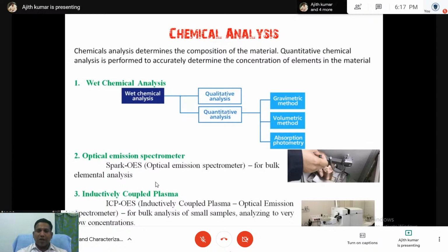The second one is chemical analysis. We can analyze the composition of a particular metal piece using chemical analysis, that is wet chemical analysis. Wet chemical analysis can be classified into qualitative and quantitative chemical analysis. Then optical emission spectroscopy gives bulk elemental analysis. If you make an aluminum, magnesium, strontium, silicon alloy by casting, the final composition we reach can be checked using optical emission spectroscopy and inductively coupled plasma spectroscopy.